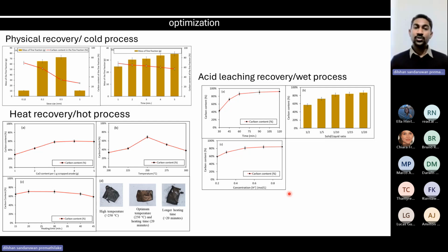The main reason is that I tried to use different acids. Actually, I tried sulfuric acid and then hydrochloric acid, and I also tried nitric acid. But all these options are not viable. For example, if I use sulfuric acid or hydrochloric acid, I have to use elevated temperatures, and I also have to use oxidizing agents, as Lucas already explained in the previous examples. The thing is, if I use these oxidizing agents or elevated temperatures, my environmental impact is going to be quite high for this process. But if I use nitric acid, the problem was that it gives a vast amount of nitrogen dioxide, which also elevates the environmental footprint of the process.